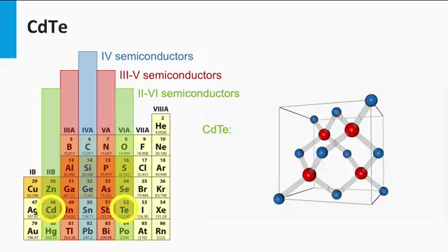This semiconductor material consists of the 2 valence electron element cadmium and the 6 valence electron element tellurium. Its network is a cubic tetrahedral lattice structure where every cadmium atom is bonded to a tellurium atom. A lot of the research activities on cadmium telluride have taken place on industrial level, and First Solar is the leading company in the cadmium telluride technology.